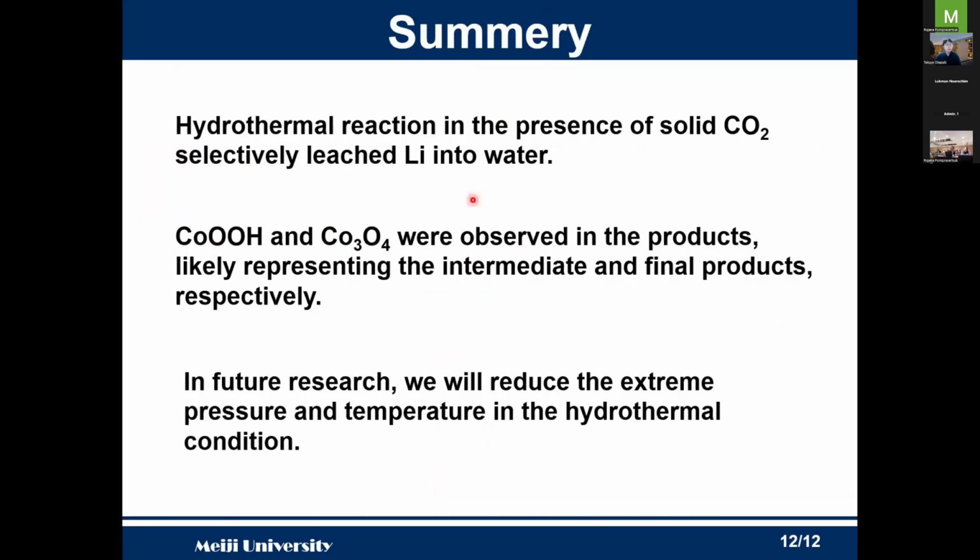In summary, the hydrothermal reaction in the presence of solid CO2 selectively leaches lithium into water. Cobalt oxyhydroxide and cobalt oxide were observed in the products, representing the intermediate and final products, respectively.